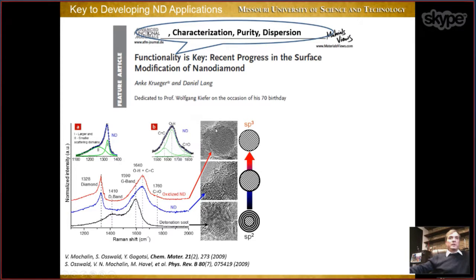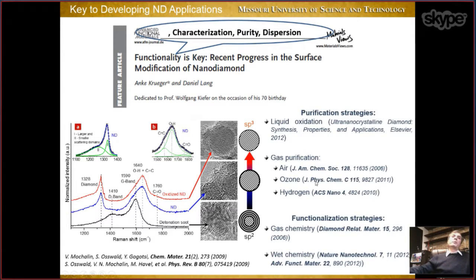for this material and for this material on top. And then you will start seeing more and more pronounced diamond peak. So everything is okay with the material. It's still nanodiamond. You just need to keep in mind that, again, this is a material, not a molecule, it doesn't have fixed composition. So this material has much more non-diamond phase, which you have to remove if you want to work with nanodiamond. And when you remove it, you get all typical signals in Raman spectroscopy and in TEM, typical for nanodiamond. Which brings me actually to the next important thing, purification.